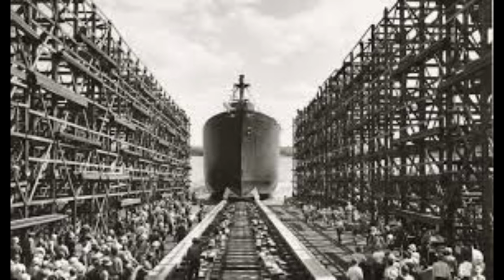Investigations after early fractures focused on the shipyards themselves, which often used inexperienced workers and new welding techniques to produce large numbers of ships in great haste. But Cambridge University researcher Constance Tipper demonstrated that the fractures were not initiated by welding defects, but by the grade of steel used, which suffered from embrittlement in the cold temperatures of the North Atlantic. The steel itself changed from ductile to brittle at certain temperatures, and the welded construction simply allowed those failures to cascade. One common type of crack originated at the square corner of a hatch that coincided with a welded seam, with both the corner and the weld acting as stress concentrators.